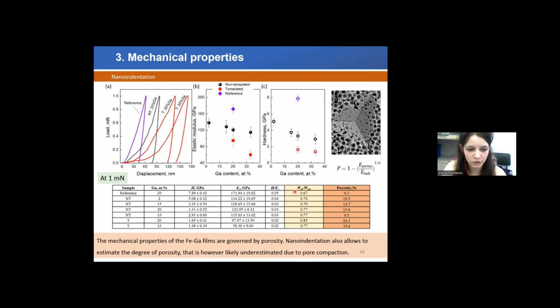This parameter shows the ability of the material to absorb plastic deformations. So even though the hardness and elastic modulus decrease, the plasticity index is increased for the nanoporous and highly porous samples. From the nanoindentation data, we could also extract the porosity degree according to this equation here. According to those calculations, the nanoporous films have about 20% porosity, while the templated highly porous films have about 35% porosity.